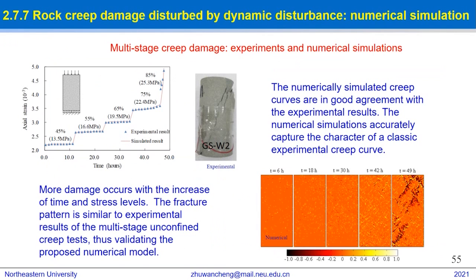This slide shows the experimental and numerical results of multistage creep damage. First, the numerically simulated creep curves are in good agreement with the experimental ones. Second, more damage occurs with the increase of time and stress levels. The fracture pattern is similar to experimental results of the multistage, unconfined creep tests, thus validating the proposed numerical model.